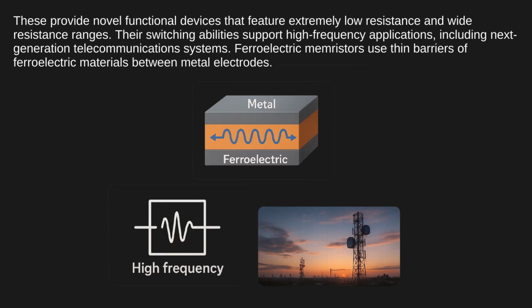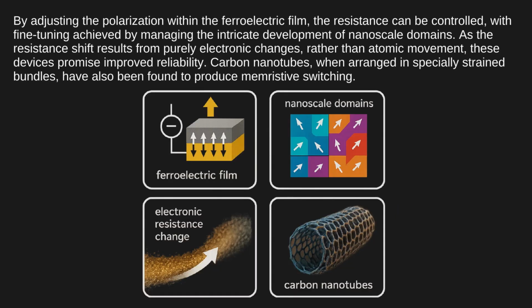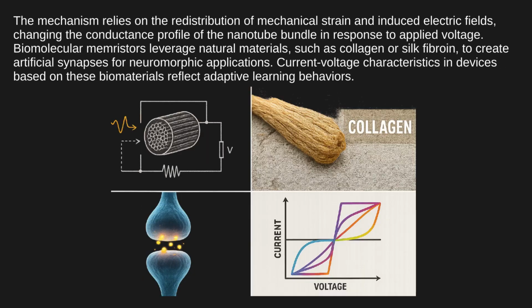Ferroelectric memristors use thin barriers of ferroelectric materials between metal electrodes. By adjusting the polarization within the ferroelectric film, the resistance can be controlled, with fine-tuning achieved by managing the intricate development of nanoscale domains. As the resistance shift results from purely electronic changes rather than atomic movement, these devices promise improved reliability. Carbon nanotubes, when arranged in specially strained bundles, have also been found to produce memristive switching. The mechanism relies on the redistribution of mechanical strain and induced electric fields, changing the conductance profile of the nanotube bundle in response to applied voltage.